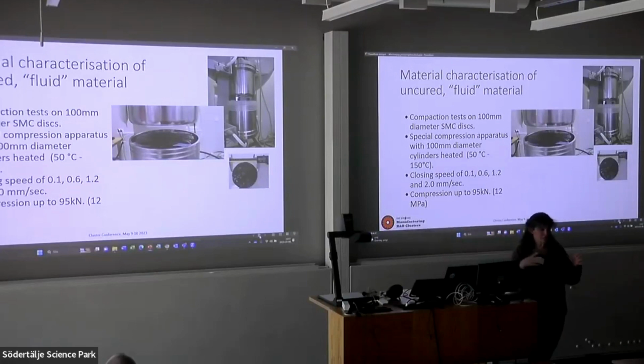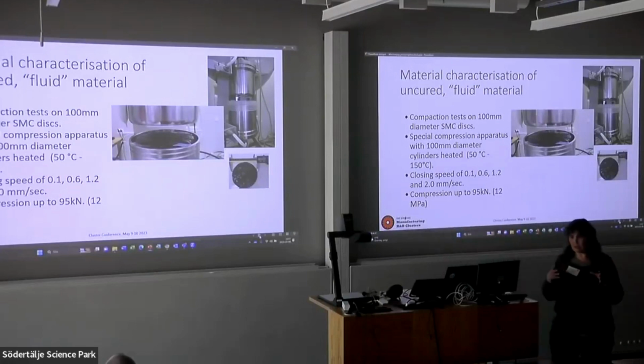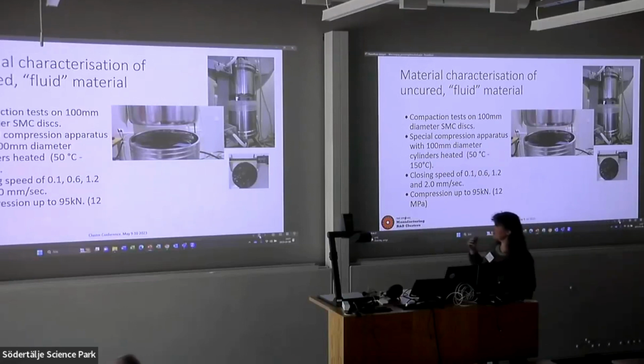It needs to be a certain size and a certain thickness because this material is inherently inhomogeneous. And if we don't start taking very, very thin layers, we end up with very uneven properties. So it's about 100 millimeters in diameter, and only one layer, so that we don't have effects of number of layers gliding over one another, because that makes it a bit more complex. We have different closing speeds, and we have the limitation on the amount of force that we can use there.